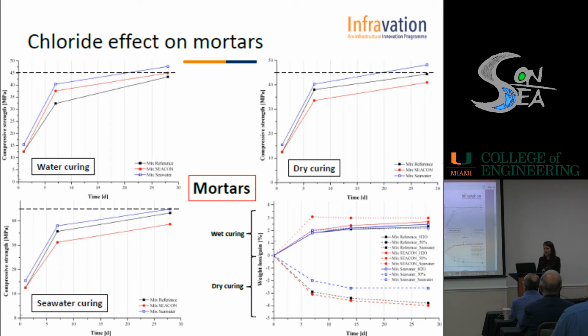As we can see from the graph, the chloride effect on the compressive strength is not so important, except for mix SEACON. In fact, in this case, when chloride is present in the cement, we have a slight decrease in the compressive strength, particularly in the case of seawater curing. And this could be due to the higher absorption of water that you can see from the fourth graph. Another important thing is that, considering the loss of weight in dry conditions, mix seawater has the lowest loss of weight. Maybe this is due to the fact that the pores are full of salts in this case, and so the loss of water is lower compared to the other two cases.